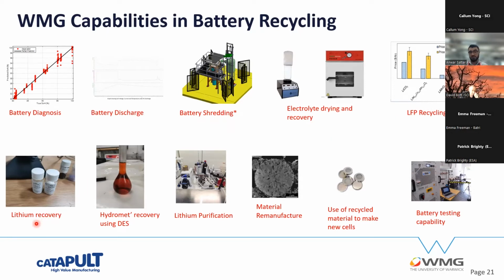We've already developed a lithium recovery process, for which we've applied for a patent, so we can recover around 95–96% of the lithium at 99.7, 99.8, 99.9% purity. We're looking to scale that up as well. We're also developing hydrometallurgical recovery processes using deep-eutectic solvents or conventional acids. And again, we've got some really promising results in that area, looking at lithium purification. The lithium that we recover here, we can purify to 99.9%.